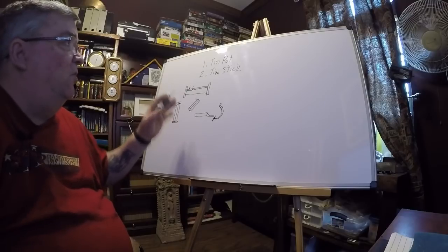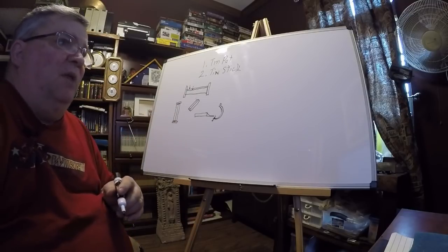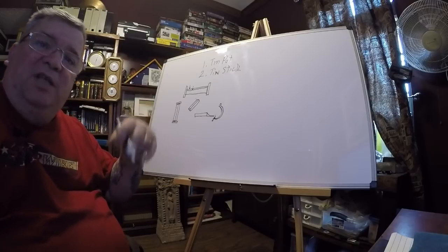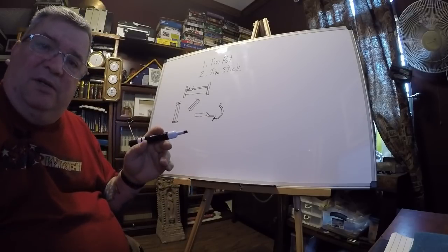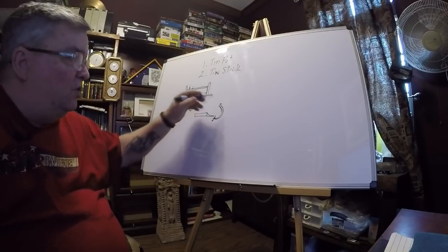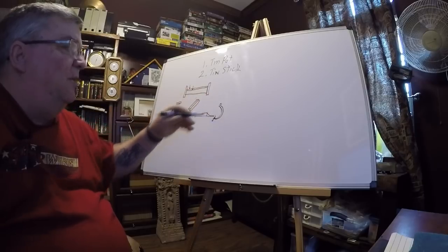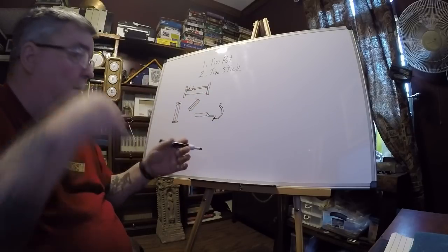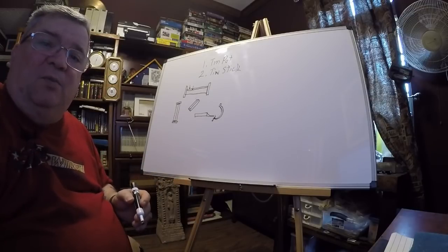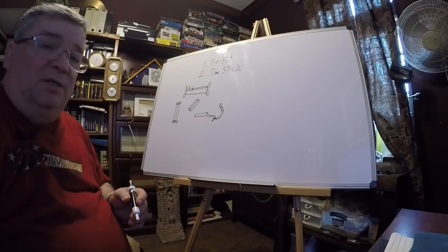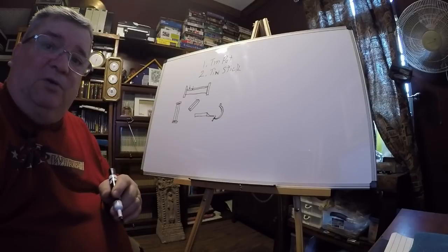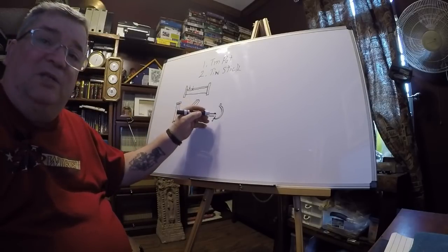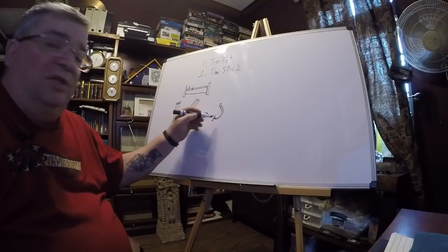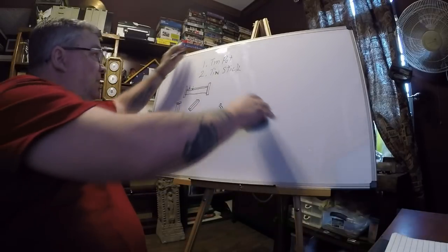There are other ways too. For instance, I have seen people with a spreadable tin. It's almost like a flux, but it's basically a tin coating that you can spread, and once you heat it up, it melts and spreads out, coating the areas you applied it to. As long as the tin coating is pure enough and doesn't have a bunch of other chemicals in there, the bearing will adhere or mix with that tin, which has bonded with the steel. That's the tin portion of it.